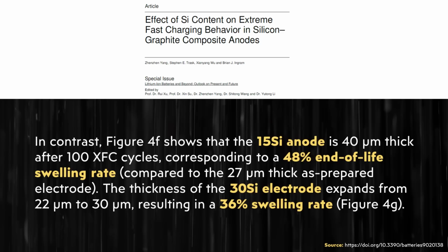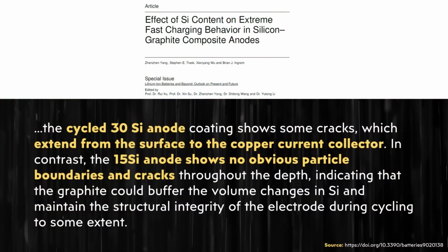When it comes to the 15% silicon anode, there was a 48% end-of-life swelling rate, and the 30% silicon anode, after cycling, resulted in a 36% swelling rate. I did find it interesting that the 30% silicon anode actually had a lower percentage of swelling versus the 15% battery. That is really interesting. But nonetheless, more importantly, when it comes to damage caused by this swelling, in their test, the 30% silicon anode coating did show cracks, and specifically here it's written, quote, "which extend from the surface to the copper current collector."